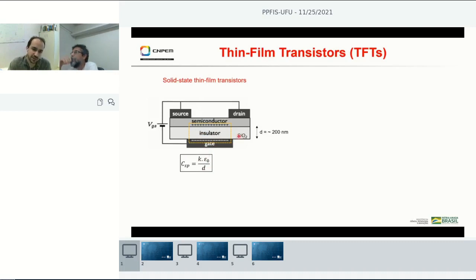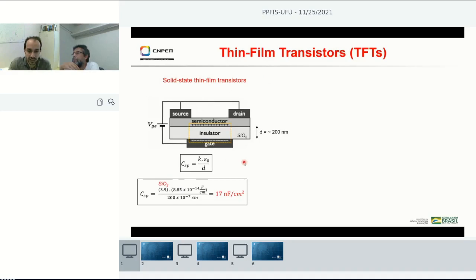Typically for electronic circuits, we have thin films of silicon dioxide as insulator, with thickness, for example, in the range of 200 nanometers. By doing a simple math, we arrive here that typically these kind of thin film transistors, in what I called here solid-state thin film transistors, may have capacitance in the order of tens of nanofarads per centimeter squared.